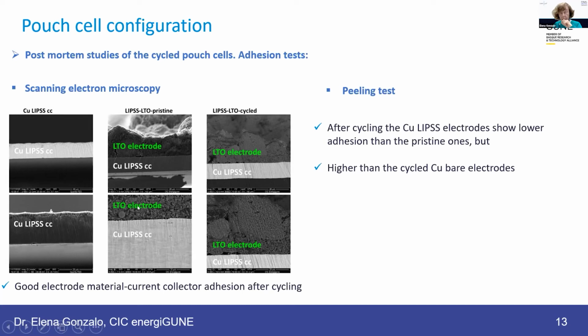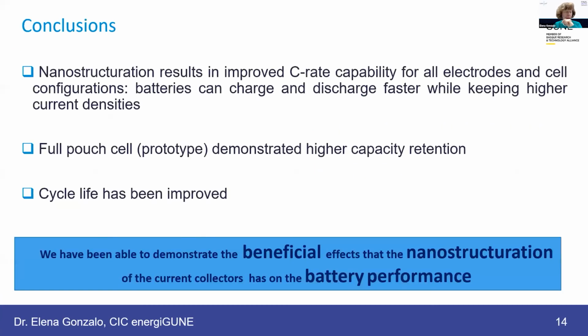And when we were doing the peeling test, after cycling these copper LIPSS electrodes, although there was a lower adhesion than the pristine electrodes, it was much higher than the cycled pouch cells with copper bare electrodes. So in order to conclude, I would like to say that the nanostructuration results in an improved C-rate capability for all electrodes and cell configurations.